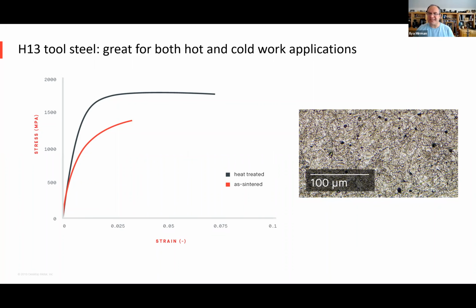So one of the materials available is H13 tool steel. So this is great for both hot and cold work applications. In another second, I'll show you it actually in action for at least in one place. But you see, here's the familiar stress strain curve. Well behaved. There's the as-sintered. As-sintered, the parts come out from the furnace fully annealed with no memory of the shaping process. And in fact, if you cut and section them, you literally cannot tell X, Y, and Z axes. The grains, the crystal structure looks identical. You get 96 to 99% dense parts, and the voids are typically 5-micron voids, evenly distributed. So it's well behaved, not unlike a very fine casting.